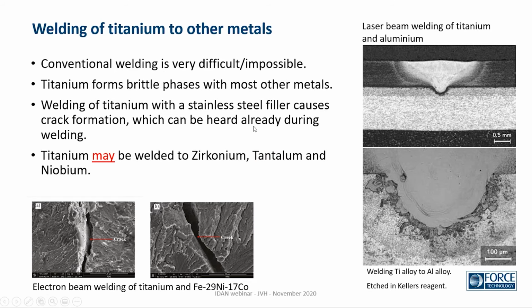Titanium is another metal which is problematic to weld to other metals. It's almost impossible to weld titanium to other metals by conventional fusion welding. We get brittle phases with most other metals. As I have read, I've not tried myself, if we weld a titanium part using stainless steel filler metals, we can hear cracks forming, creating noise during welding. There are some metals that we might be able to weld titanium with, or two.